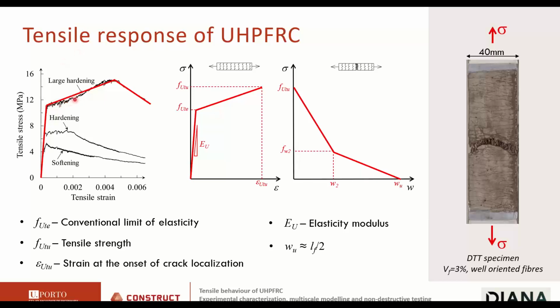This experimental curve here has been obtained in a UHPFRC with 3% of well-oriented fibers. So we managed to orient the fibers along the direction of the loading. What do you see here? You see a very tight array of cracks. Here the spacing, for your reference, if this is 40 millimeters, here we are talking about a crack spacing between 3 and 4 millimeters. What did we observe? There's the formation of the first crack, then a crack formation stage, and then the material enters the stabilized cracking stage, in which the existing cracks are opening, but no more cracks can form.